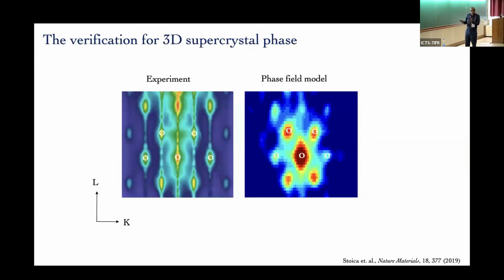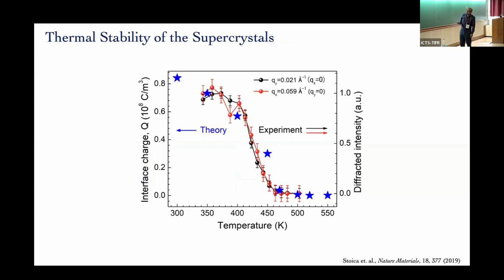We know that these simulations are okay because you can take the diffraction pattern you have measured, you can do a Fourier transform and take the diffraction pattern from the phase field, and there's some matching. Not always perfect, but they're close for all of the various cuts, of which I just showed you one cut. Now I have to tell you something, that crystal we created stays there. So you create it, one pulse of light, the supercrystal shows up and it's there, it's yours. Okay, it's good until you heat it to 450 Kelvin, then it's gone. Now if you cool it back, it doesn't come back.